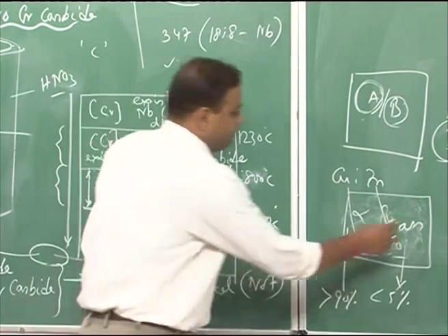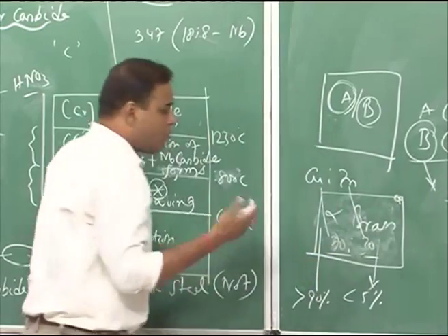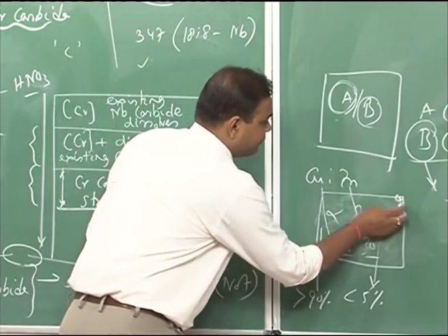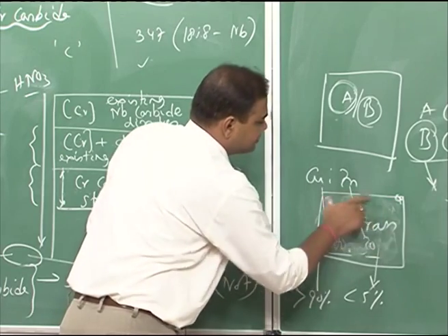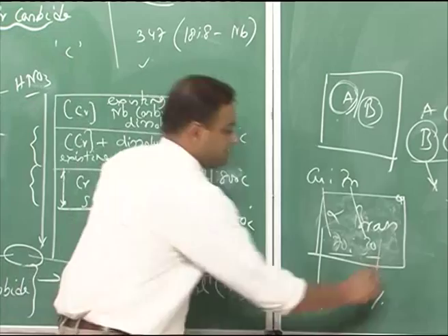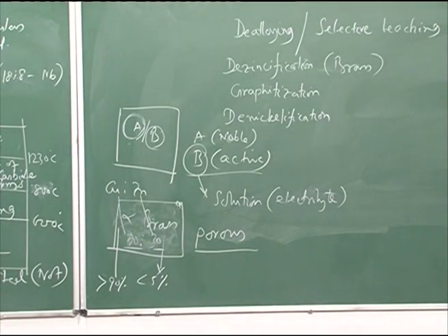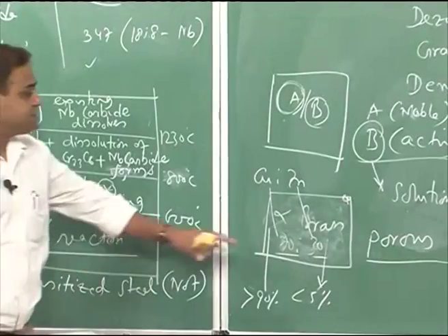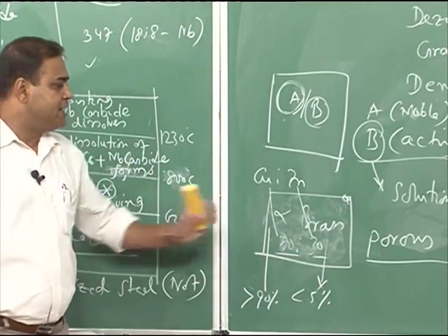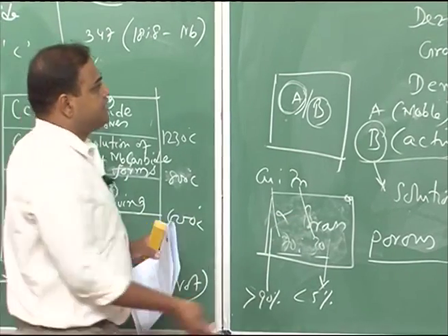The surface becomes more and more red colored, and also if we see the structure of it, that structure becomes porous in nature. So, this is a particular example where zinc dissolves preferentially, leaving copper in the material in the brass. So, this is called dezincification.